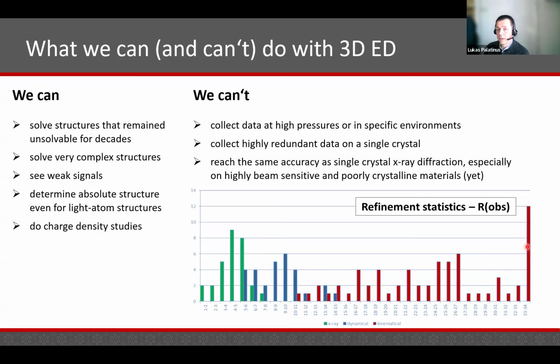What we can't do is collect data at high pressures or in specific environments. Electron diffraction data are collected essentially exclusively in vacuum. We can't collect highly redundant data on a single crystal because we have only a limited range of tilt in the electron microscope. And for now, we can't reach the same accuracy as single crystal X-ray diffraction, despite the improvements brought by dynamical refinement.